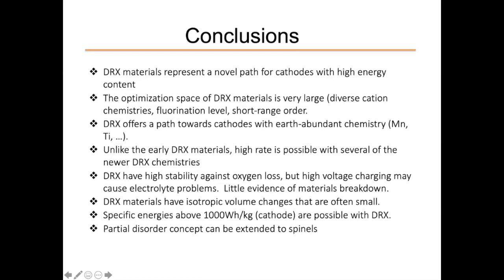And another aspect that is probably more important for solid state batteries is that DRX materials, because they are cubic, have by definition isotropic volume change, not like layered materials which are anisotropic. And they are often small. They are not always small, but we have one material that has zero volume expansion, for example.